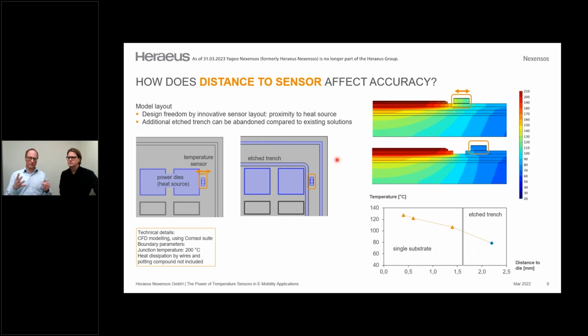What we see here is that by reducing the distance between the temperature sensor and the power die, we get even more accurate in representing the temperature of the power die, and looking at the effects of the etched trench, we see that there's a substantial drop in the temperature that we detect, which reflects the potential and possible accuracy. If you look at that graph, it's easy to understand that if you're on the left side, you have a really good idea what the temperature of the die is, and this is really essential to protect the die. On the other side, in the area where the etched trench is interrupting the heat transfer, you have only a rough idea about the temperature.